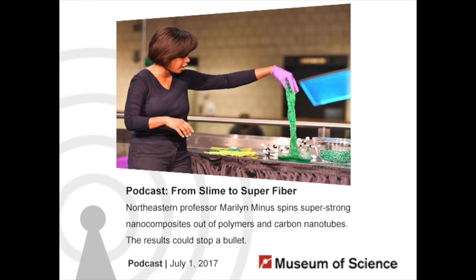So I didn't say the properties earlier, but our textile fiber is really intermediate, 0.5 gigapascals. So I can rip that. Our ballistic fiber, our bulletproof fiber, is 5 gigapascals. I can't even cut that. But a fiber that has 100% alignment, it's 10 to 20 gigapascals. You don't even have anything on Earth that is that strong.